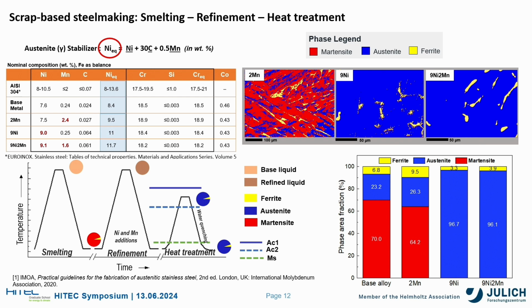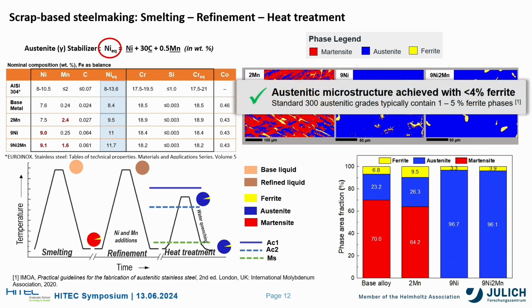So at least with these two refined alloys, we can see that we are achieving an austenitic microstructure even with the presence of these ferrite phases, because standard 300 grades may contain up to 5% ferrite. So this might be good enough for us.